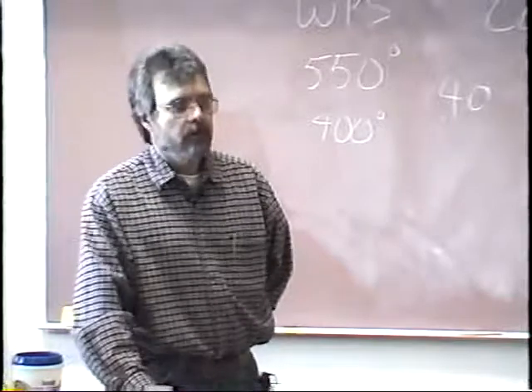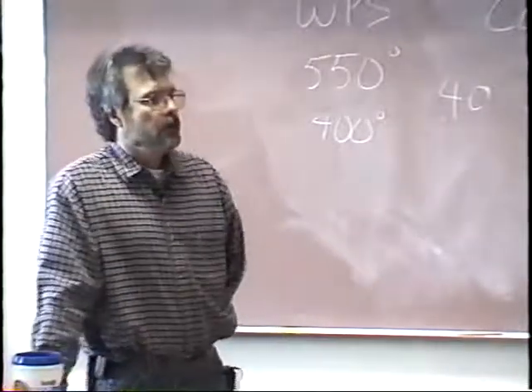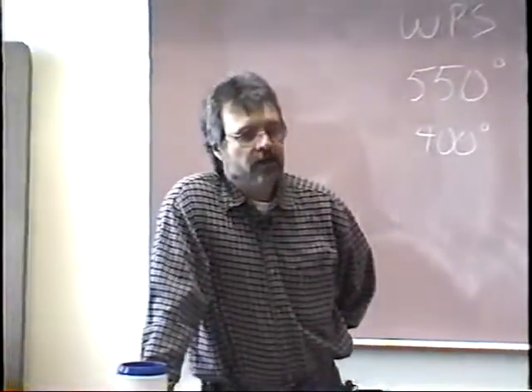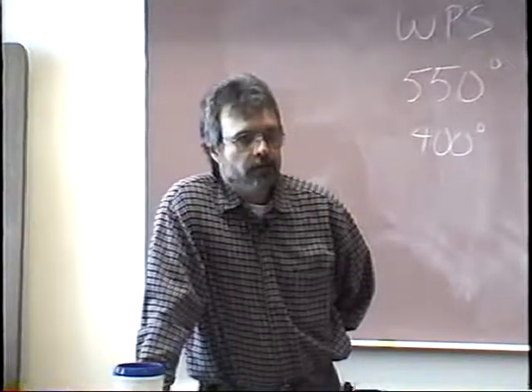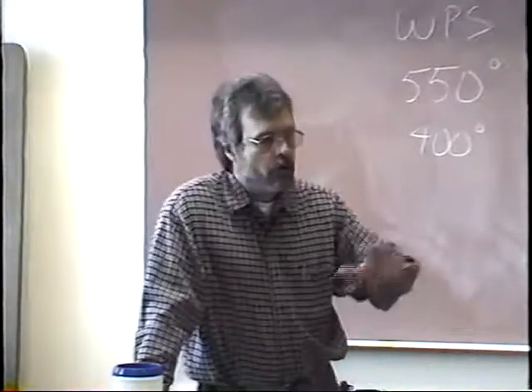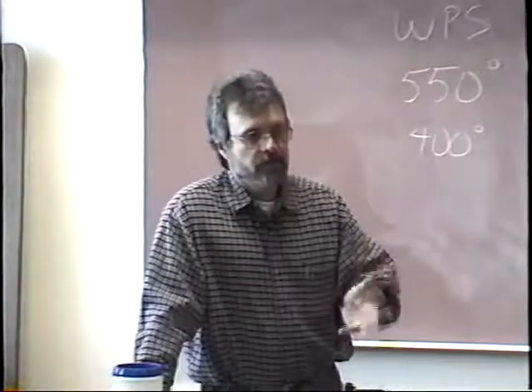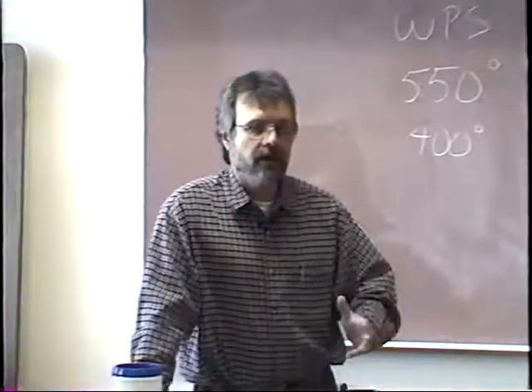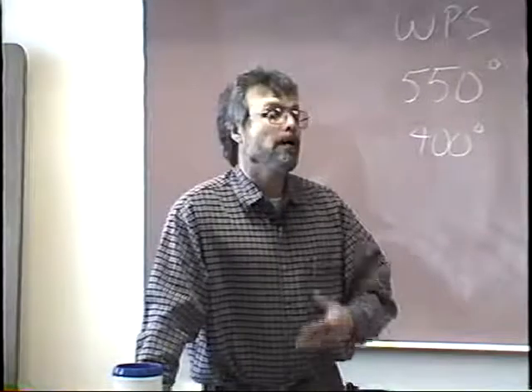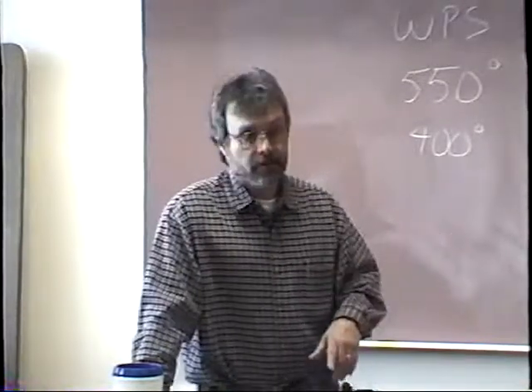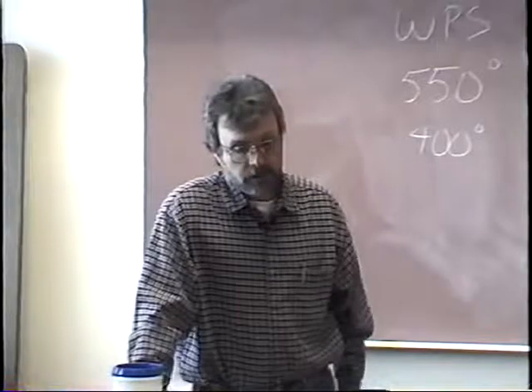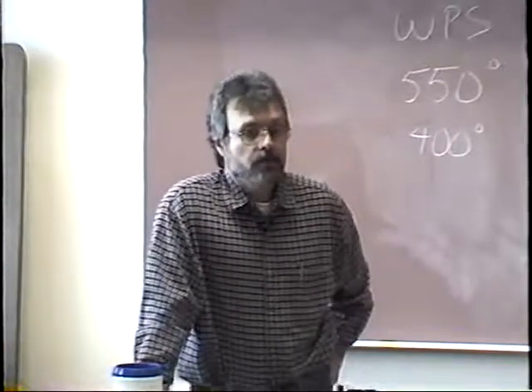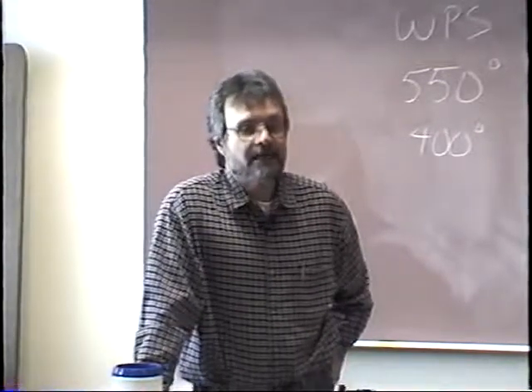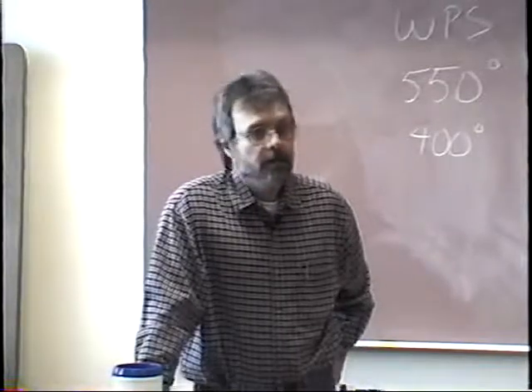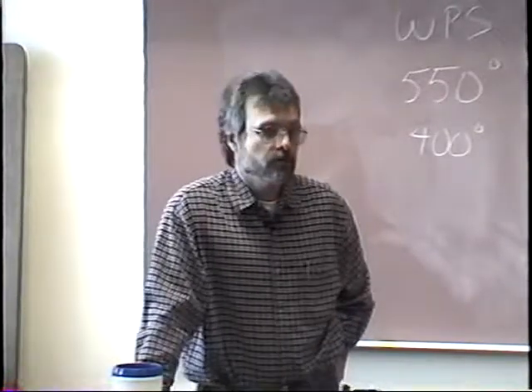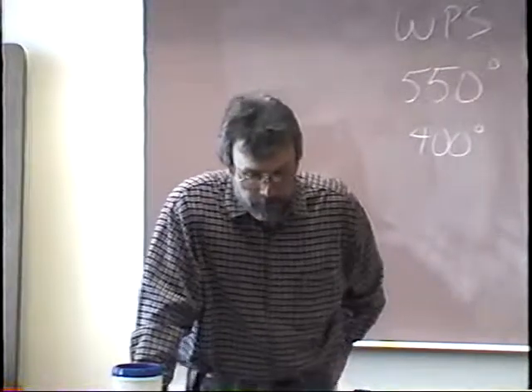And under ASME B31.3, they have a paragraph in there that talks about interrupted welding. If you're making a weld and you're recording all of that, and you're recording the time between each pass, if you go away for lunch and then come back, there are certain conditions and requirements you have to meet before you can start welding on that again, so that the notch toughness can be maintained. And generally, they require that you reheat that pipe back up to a certain temperature and maintain that temperature for a while before you start a resumption of welding.